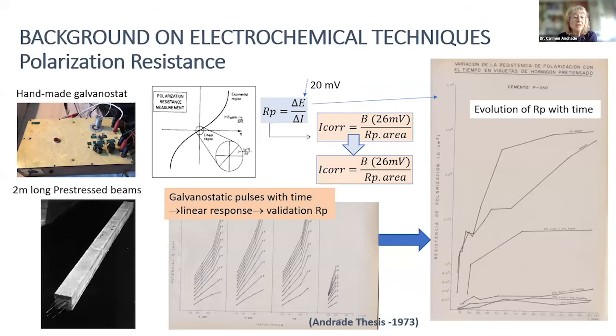This is a handmade galvanostat that we made for just doing the experiments. I used 2 meters long pre-stressed steels. I used one bar or one wire for working and the other for counter. And I was applying galvanostatic pulses in order to look at whether the response is linear or not. In that case, I was using different amounts of current and different time steps waiting in order to realize whether it is linear or not. And it's quasi-linear really. I was plotting the different Rp values, and we realized that they correlate very well to the state of corrosion of the bars inside these beams, some of which were made with calcium chloride.